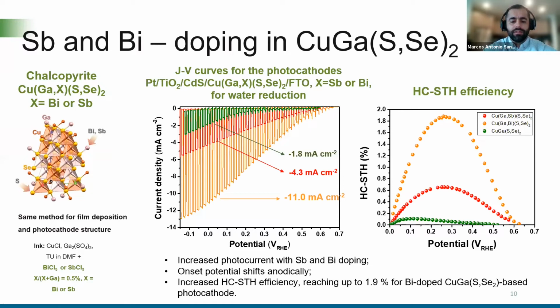So using the antimony and bismuth doped copper gallium sulfoselenide photocathodes, we obtained higher photocurrents, reaching up to 11 milliamperes per square centimeter when doping with bismuth. We also noticed the onset potential shifted more positively, and we reached a half-cell solar to hydrogen efficiency of almost 2%. With that, we achieved a new photocurrent world record for water reduction reaction using copper gallium sulfoselenide photocathodes.